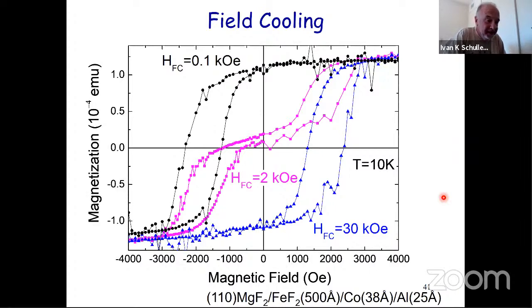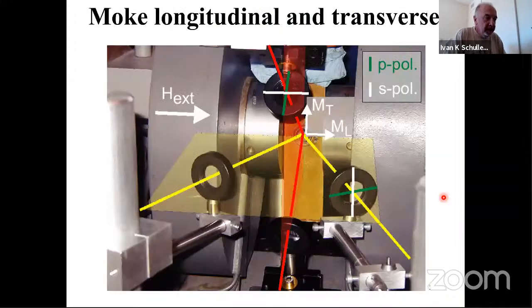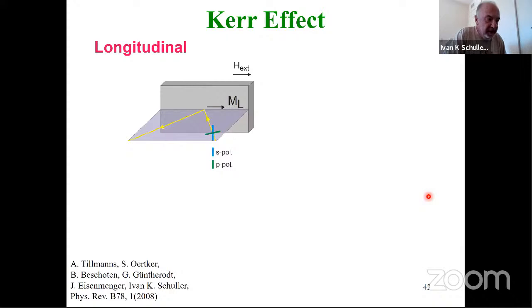Okay, so it's complicated. Now, the reason that this happens is because the magnetic moment of the surface couples to the external field, which is something that will probably be used for what is called antiferromagnetic spintronics, but I will not tell you about that yet. There's another thing: if you try doing longitudinal and transverse MOKE, what you discover is the following. This was a technique that we developed a long time ago, and then later on we applied it to this.